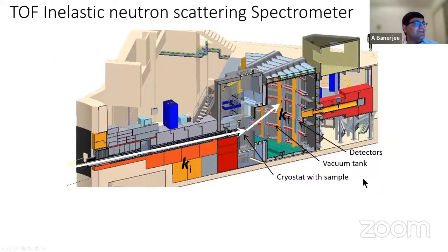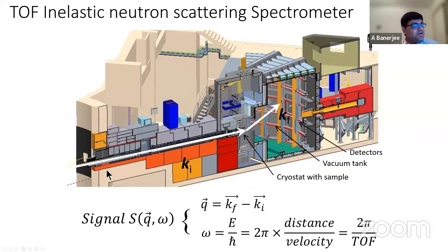So this is how a typical experimental end station looks. The neutron comes, and this is the size of a man, and this is how big this instrument is. Your cryostat sits with your sample in a vacuum chamber right here. This is a staircase. You go down here. There is a lot of shielding material here because, as you know, these neutrons are fast and can make everything radioactive around you. So you have to shield everything quite a bit. There is a huge vacuum drum, and beyond that vacuum drum, you have your helium-3 detectors, and this whole vacuum drum is maintained at a very high vacuum with huge vacuum pumps. And what happens is that an incident neutron with incident momentum Ki hits your sample, which sits right here. It goes and hits the detectors with a final momentum Kf. From looking at Ki minus Kf, so from where the neutron hits, you get the momentum.